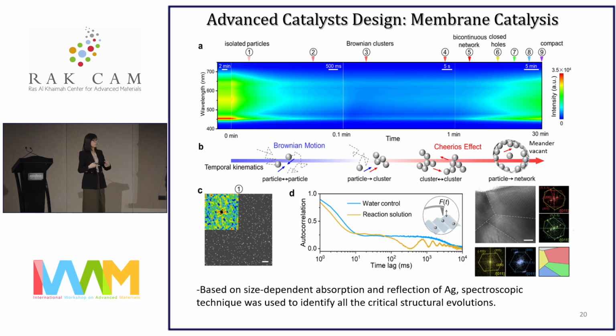initial aggregation as well as transformation into 2D clusters. And followed by that, we have the capillary attraction, also known as the Cheerios effect, that would drive the self-assembly of these isolated Brownian 2D clusters to mutually attract and then form a quasi-bicontinuous network. And thereafter, the meander-shaped vacant regions are progressively filled up by the particles and evolve into well-defined closed through-hole pores. And if this process is allowed to continue, the holey membrane will eventually become a compact membrane. So the quasi-bicontinuous network is shown to be isotropic and also fractal in nature, which is evident from the TEM images here. And these basically confirm that it is derived from a combined Brownian and Cheerios effect rather than from a single dynamic mechanism.